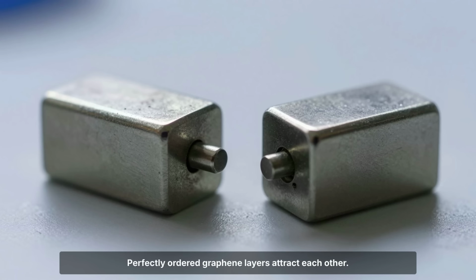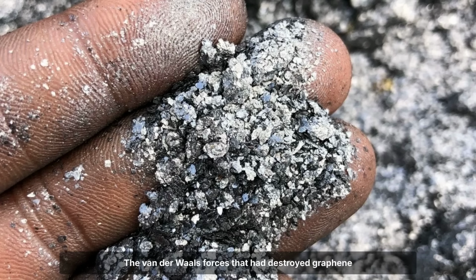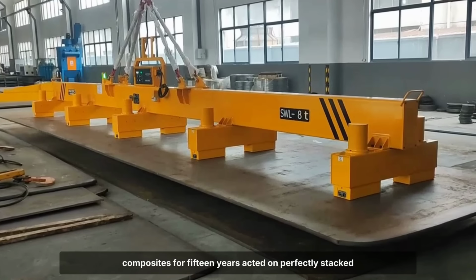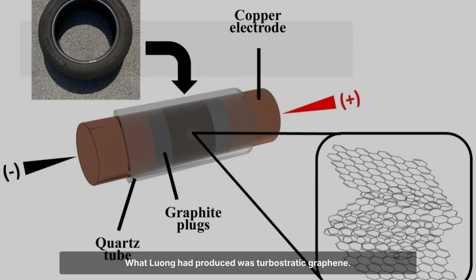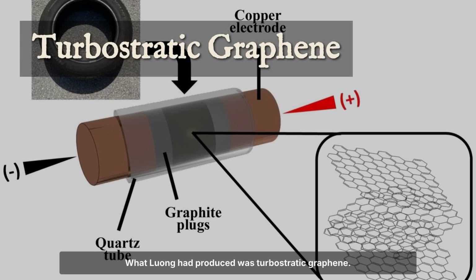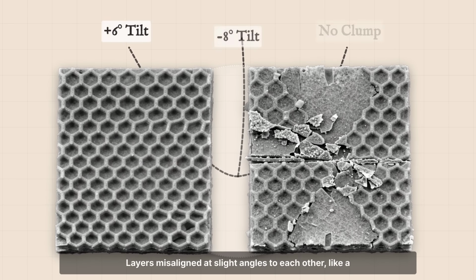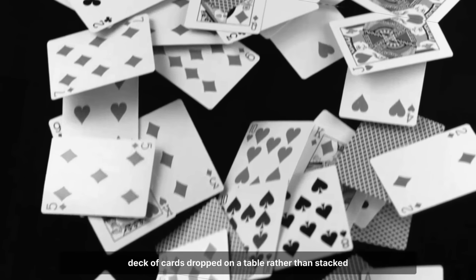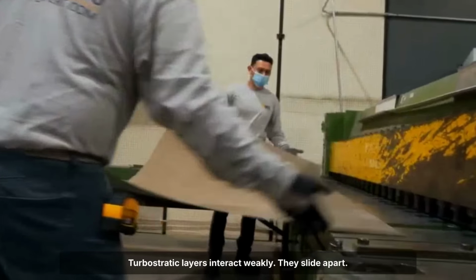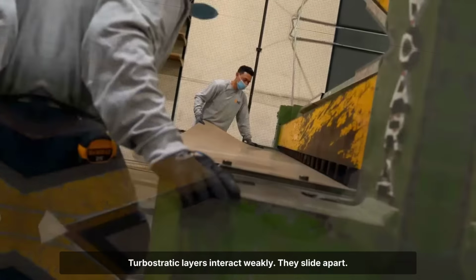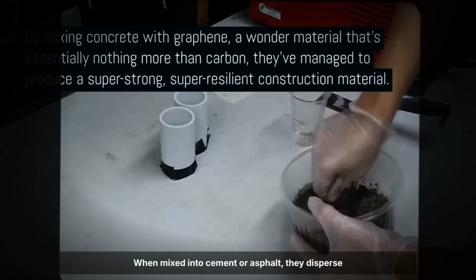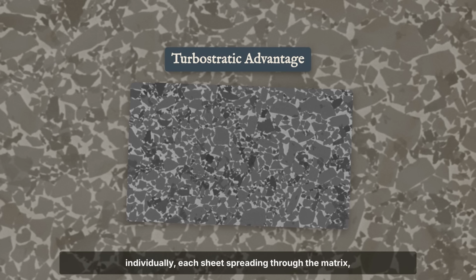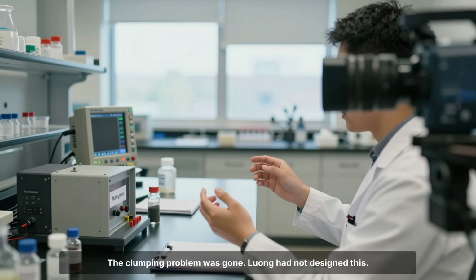Here's what I mean. Perfectly ordered graphene layers attract each other. The Van der Waals forces that had destroyed graphene composites for 15 years acted on perfectly stacked graphene like a magnet. What Luong had produced was turbostratic graphene: layers misaligned at slight angles to each other, like a deck of cards dropped on a table rather than stacked perfectly. Turbostratic layers interact weakly, they slide apart. When mixed into cement or asphalt, they disperse individually, each sheet spreading through the matrix, bonding to the surrounding material, reinforcing the composite at the molecular level. The clumping problem was gone.